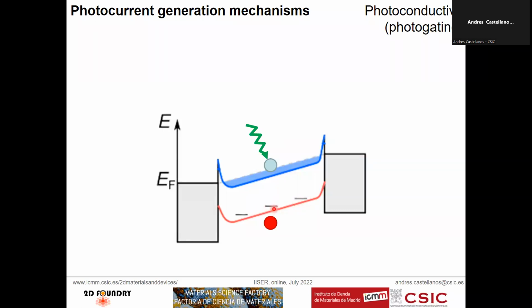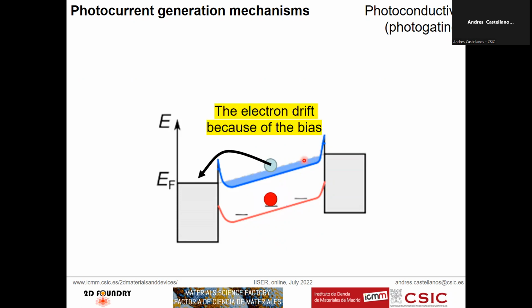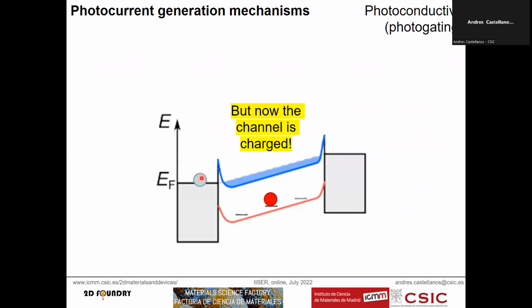Now in the case of photogating, as these two-dimensional materials have this sensitivity to trap charges because they are all surface, they are really close to the traps that are at the interface. So you can have these states here that can trap the minority charge carriers. In the case of molybdenum disulfide, which is an N-type semiconducting material, you can easily trap holes. And once you trap this hole, this electron feels the drift because of the bias difference between the electrodes. So basically it will jump here to the drain electrode.